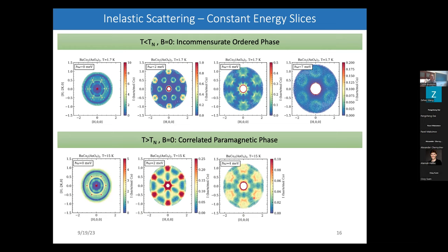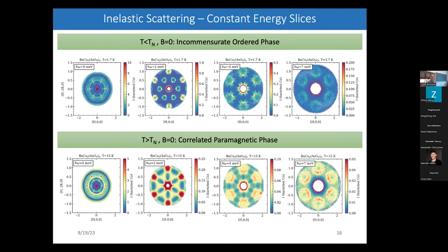I think the intensity is actually quite different, but the overall pattern looks fairly similar. And then I come up to higher energies, and then I have a quite significant similarity between what happens at low temperatures and at high temperatures. But I mean, this is not to say that I have spin waves, but I have some kind of paramagnetic, paramagnon type fluctuations that look a little bit like what you'd expect for a system that's near ferromagnetic instability.